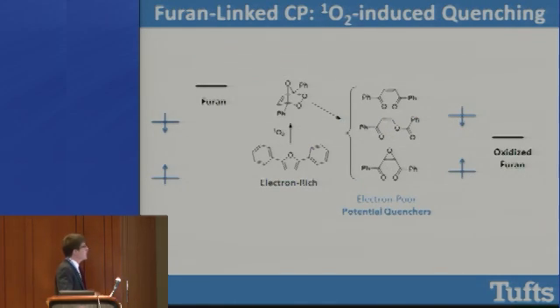And so what I'm going to do here is tell you about a project that was just completed and that we recently published, where we use furan derivatives, and furan derivatives undergo cycloaddition reactions with singlet oxygen to form this intermediate endoperoxide. Now, the furans that we're starting with are relatively electron-rich. They don't really want to accept electrons very readily. And so that unoccupied orbital of the furan is pretty high in energy up here, significantly higher than the excited state electron of our fluorophore.